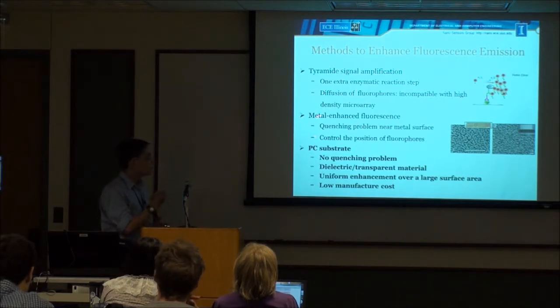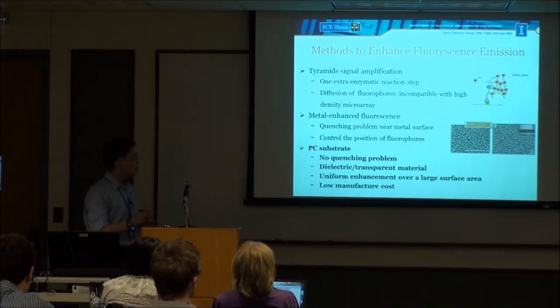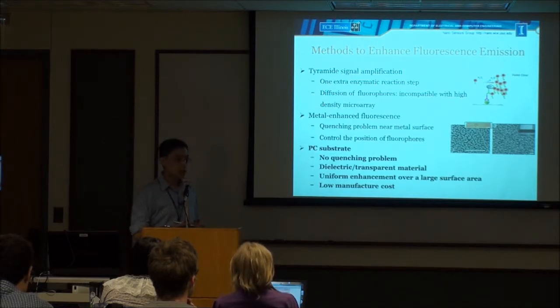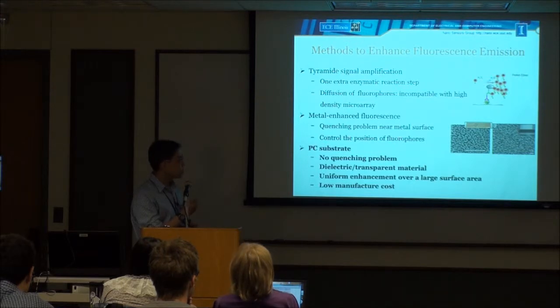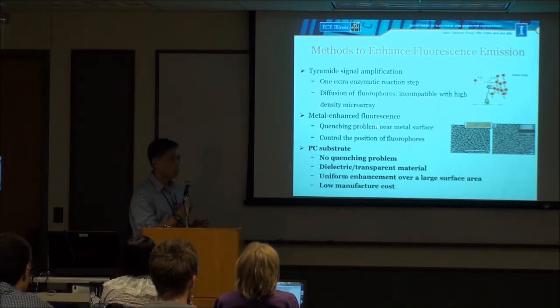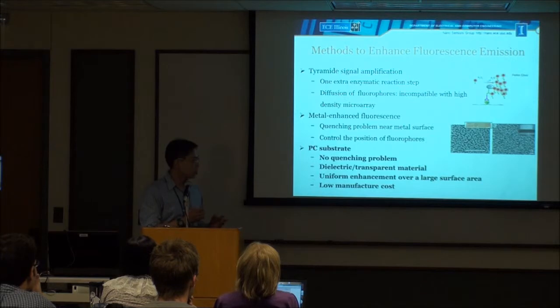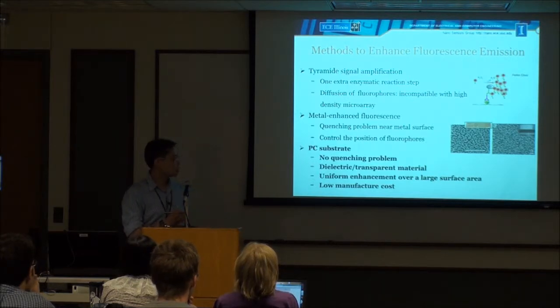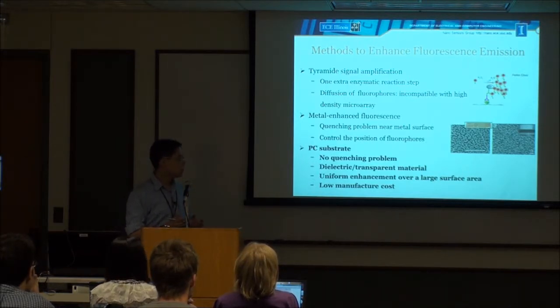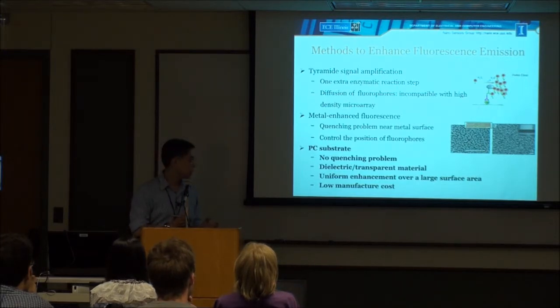Another method is metal enhanced fluorescence. Metal enhanced fluorescence has been extensively studied, but this method suffers from the quenching problem, which means if a fluorophore gets very close to the metal surface, the emission of those dye molecules will be quenched. So people have to precisely control the position of the dye molecule. If the molecule is too far from the metal surface, there won't be any enhancement. But if it is too close to the metal surface, its emission will be quenched.